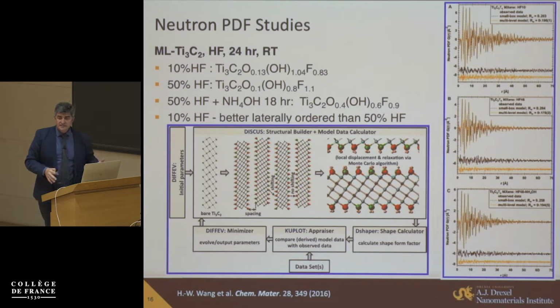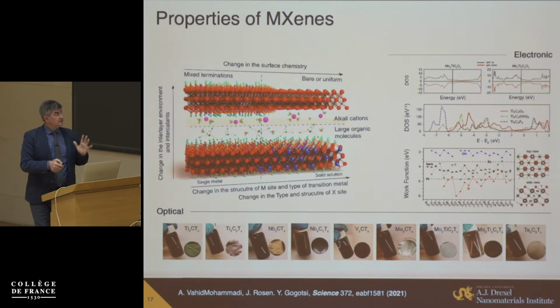And also we have done similar studies, say, on high-resolution STEM, showing that the number of vacancies in the surface layer of titanium will increase with increasing concentration of etchant here. So you can play with this. So bottom line is, we have this family of materials where you can control the properties by controlling the M element in the structure, controlling the X element.